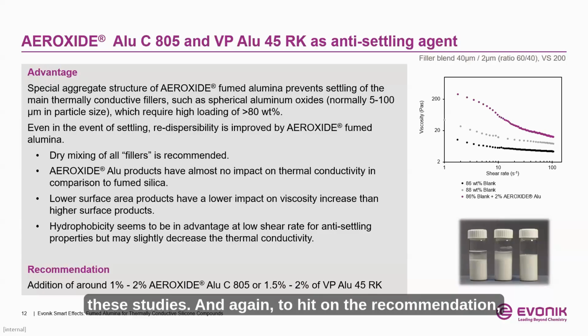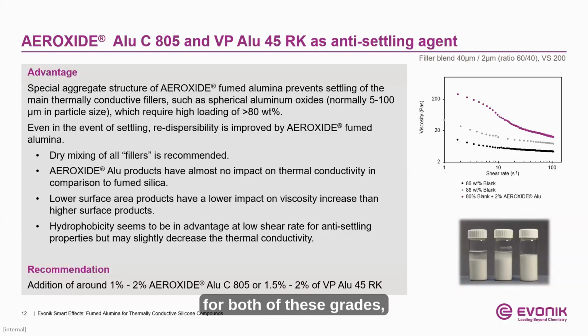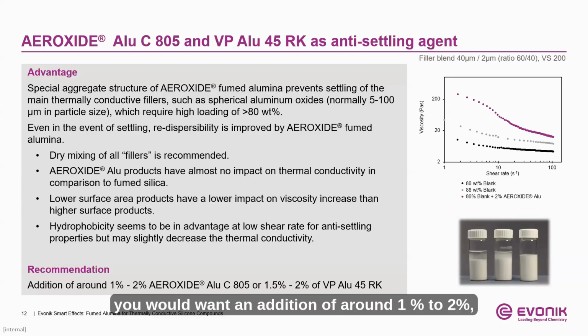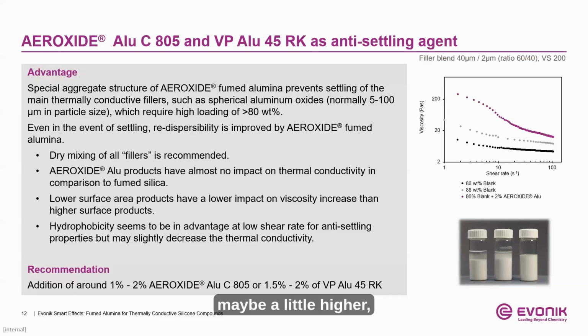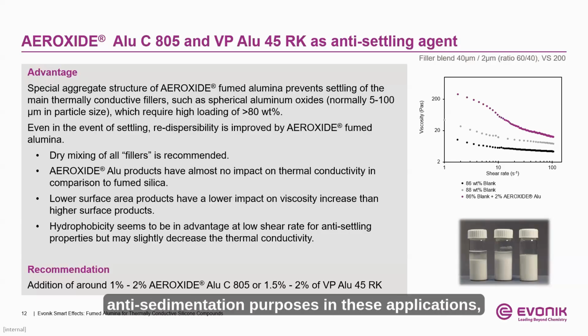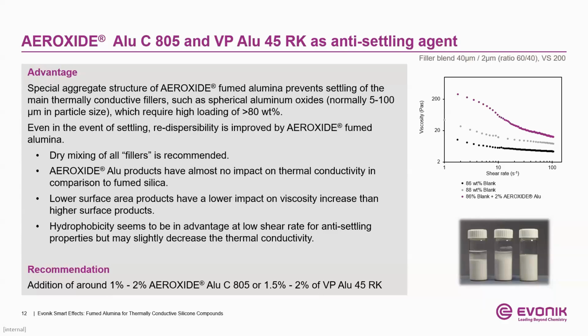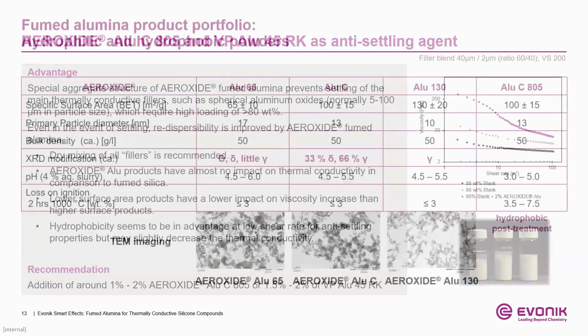And again, to hit on the recommendation, for both of these grades, you would want an addition of around 1 to 2%, maybe a little higher, 1.5 to 2% for the VP ALU-45RK, but 1 to 2% of the ALU-C805. Generally, if you're using any of these fumed alumina grades for their anti-sedimentation purposes in these applications, 2% is generally a very good starting point for either the hydrophobic or the hydrophilic grades here that we've discussed a bit today.